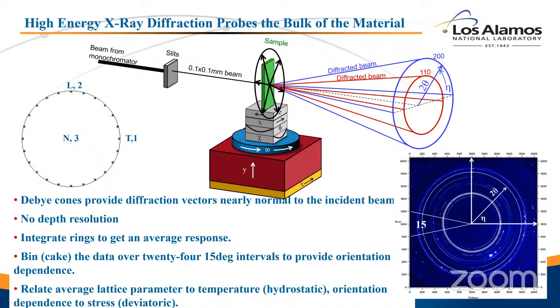So the way we analyze the data, because as I said, I want to separate a scalar effect, which is temperature, from a tensor effect, which is stress. We take these rings, and the first thing we'll do is integrate all 360 degrees about the angle eta that I've defined on that picture. That gives us the average lattice parameter, and that's what's related to the temperature. You can go through the mathematics, I won't do that here. Then we break up that ring into 24 15-degree increments, call that caking. It's because the program was written by an English guy. If it was written by an American guy, it'd be called PIE, which is a lot harder to say than caking. But anyways, we cake it into 15-degree intervals, and then we get a lattice parameter as a function of angle, and that's what gives us the tensor part, the stress. Okay, so that's how we separate those things.